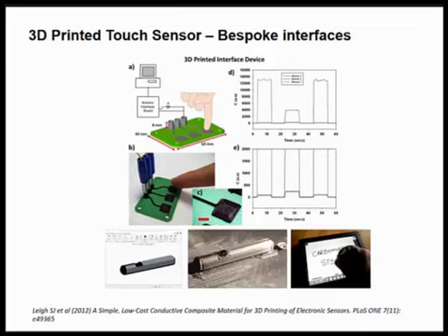Using the same material, but in this case to make interface devices. So this is a single print build, two material, probably 25 minutes, half an hour. The green material is just an ABS, the black material is our carbon-loaded thermoplastic. Depositing that, again, banana plug straight in the back, and using it as an interface device, looking at the capacitance change when you touch it.